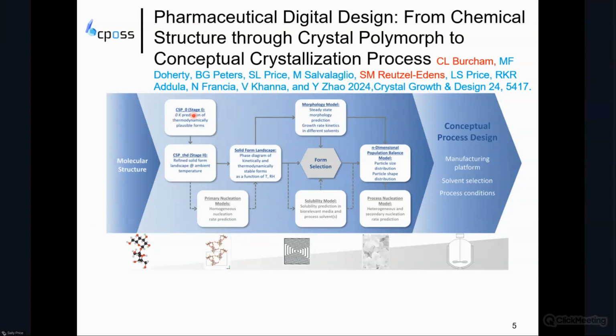Conceptually, you'd use crystal structure prediction to find the possible forms, refine the thermodynamics to get your landscape and phase diagram of the possible structures, use these to calculate the morphologies and the growth rates in different solvents, the solubility in different solvents, and also in biorelevant media, and select which structure you wanted to manufacture. And you can put all these parameters into a chemical engineering n-dimensional population balance model to predict the resulting particle size distribution and particle shape distribution, and therefore choose your manufacturing product, solvents, process conditions for that molecule, or decide that it's going to be too hard to process.